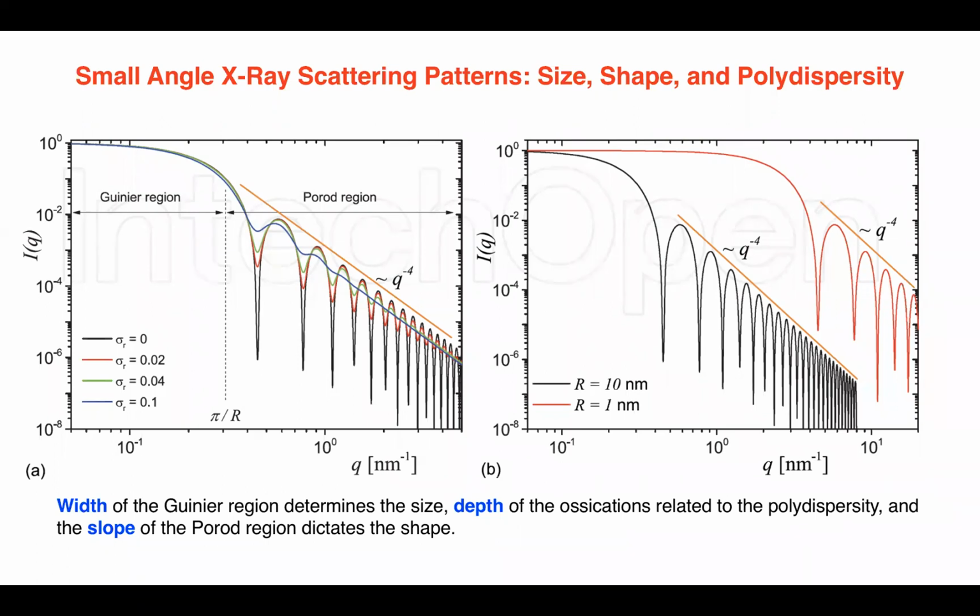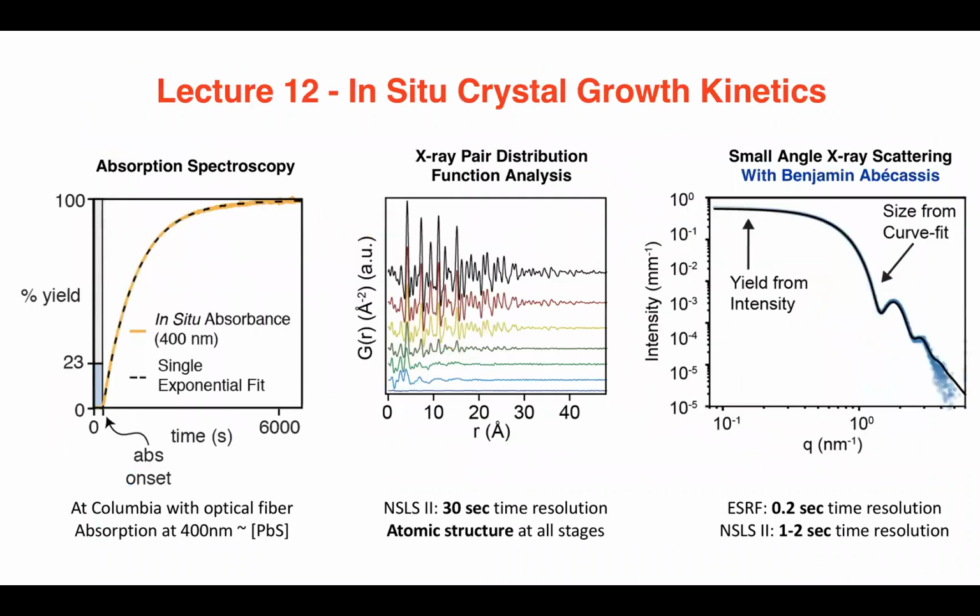So the first time I saw these patterns, I was confused about all this stuff. I'm now really intuitive about the log scale of intensity versus Q, and know that spherical scatterers have this shape, rods have another shape, platelets have another shape, and you can model these lines to extract shape and size and polydispersity. You can have an ideal sample, like nanoparticles of the type people think of in photosynthesis, they are sort of idealized, and you can get a lot of information about them by modeling that shape.